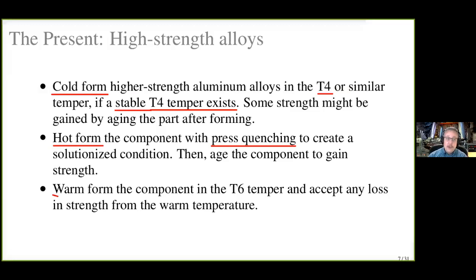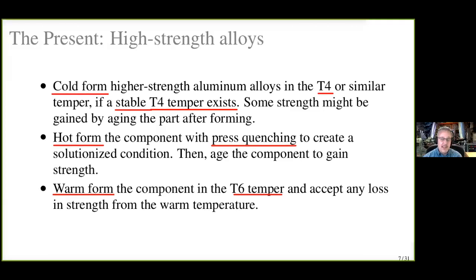An alternative is to go to warm forming. That's the 200 Celsius kind of temperature for 7075. And you start off with a T6 temper, and you simply accept any loss of strength that you have while the part's warmed for warm forming. And BMW actually was making a component for the BMW i8 sedan, which is one of these super $100,000 plus sedans that's hybrid, I believe. Actually, a contractor was making a small door beam for crash protection out of 7075. And I actually talked with the engineer from the Austrian aluminum company that's producing that material, and they were basically not able to figure out how to control that strength loss very much, is my understanding.